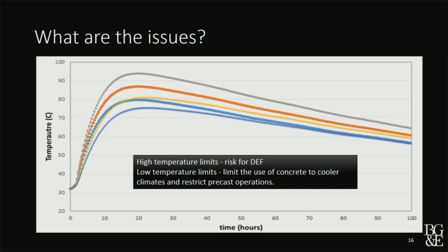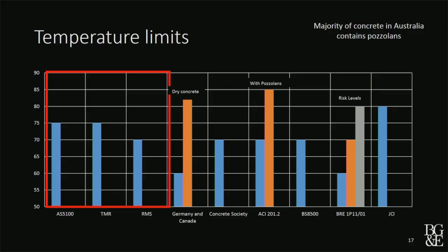When we look at temperatures in mass concrete, we can change it using pozzolans, we can reduce the temperature, but sometimes we just can't get the concrete cool enough to meet very restrictive temperature restrictions. So when I looked at the temperature limits that were worldwide and those that are in Australia, typically Australia has adopted lower restrictions for temperature than they have elsewhere. And the difference typically at 75 degrees is out of AS 5100, 70 degrees appears in some of the government specs. It makes it very difficult to place concrete that's sort of 2 metres thick without exceeding those temperatures. You're looking at having to reduce your concrete temperatures down to something like 26 degrees.